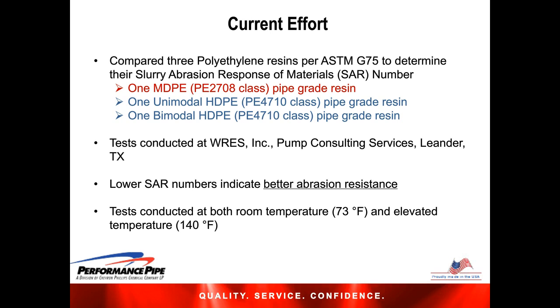The tests were conducted at White Rock Engineering Services based in Texas. In the results that you are going to see in the next couple of slides, bear in mind, please, that a lower SAR, or slurry abrasion response number, indicates better abrasion resistance. To cover the effects of temperature, we did the test at both room temperature, 73 degrees Fahrenheit, and the elevated temperature of 140 degrees Fahrenheit.